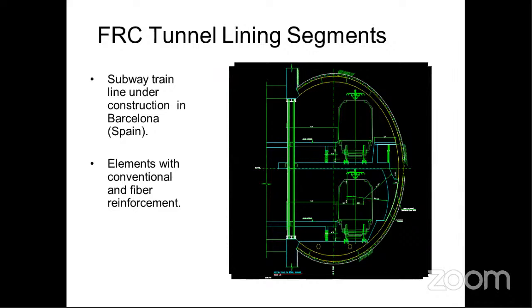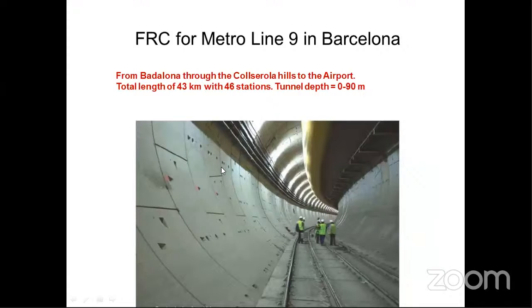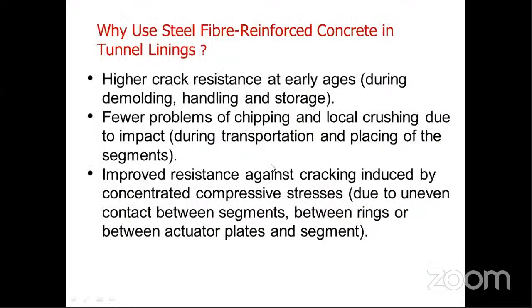And FRC tunnel lining segments also find wide applications in the construction industry. In Barcelona, Spain, this entire tunneling has been constructed with SFRC for a tunnel depth of 0 to 90 meters, because these are the precast segments. Why we are using precast segments for tunnel lining is that there may be a problem of chipping and local crushing when the trains are moving. So to avoid this type of failure and to improve the crack resistance at the early ages, SFRC has been used as a tunnel lining material. And there will be a lot of compressive stress maybe induced because of the uneven contact between the segments. So for this purpose, steel fiber reinforced concrete tunnel linings have been used.